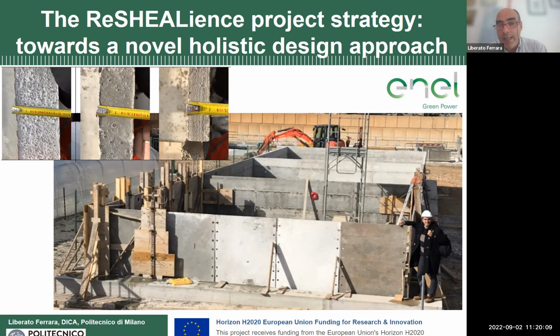And then we said, okay, why don't we go for some site precasting? So we designed slabs to be then tilted up. Slabs you cast horizontally, you tilt them up, and you complete the basin, casting on site some columns. We call them buttresses because they function more or less like the buttresses in a Romanesque cathedral. And you can see the holes in the slabs. They were intended so that when you pour the material for the columns, the fiber reinforced UHPC material passes through them and creates a sort of concrete dowel connection between the slabs.